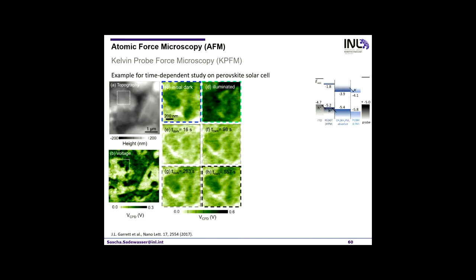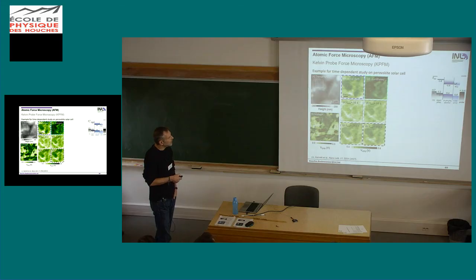So initially they measured in the dark, which is this image here, but then they illuminated for some time, and then they switch off the illumination. And then what they see is that after switching off the illumination, even after 16 seconds, you don't get the same thing. But then as they wait longer and longer, they go back to this same state.